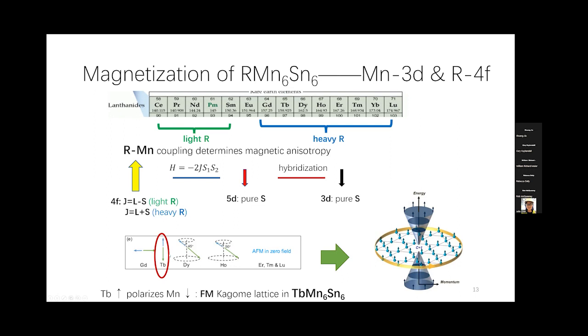one element, which is terbium, has a very strong out-of-plane ferromagnetism due to the strong anisotropy of terbium. And that terbium moment just polarizes the manganese moment, making you achieve a ferromagnetic kagome lattice out of plane. So that's the reason we chose terbium 166 as the first example to measure.